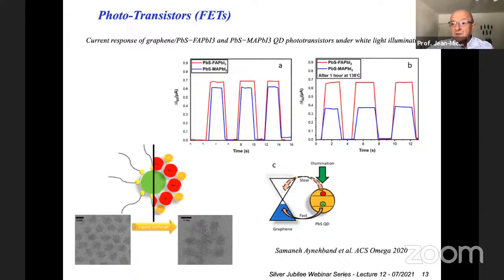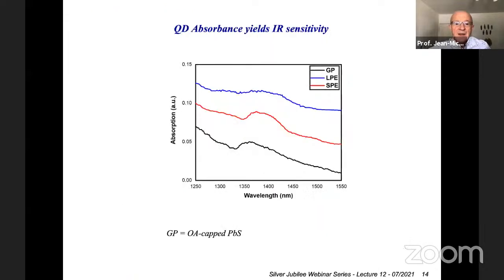We have a shift of the conductivity of the graphene, which is detected by the currents between the source and the drain. The absorbance of the quantum dot is in the near infrared. So these are infrared sensitive photodetectors. And by using different quantum dots, you can tune the absorbance into the infrared. That becomes a different kind of photodetector, because the photodetectors made from the perovskite were sensitive into the near infrared, but not well below 800 nanometers. Meanwhile, these ones can go down to 1.4, 1.5 microns. So it goes more into the infrared.